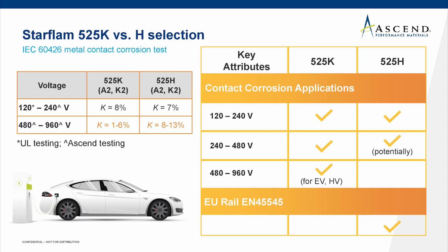And here we show a product selector, and how would you decide if you would want to use the K or the H grade. In the chart on the left, we can see the K factors at lower voltages are very comparable. But as we go to higher voltages, we consistently saw lower K factor values, so lower loss in tensile strength after aging for the K grade.